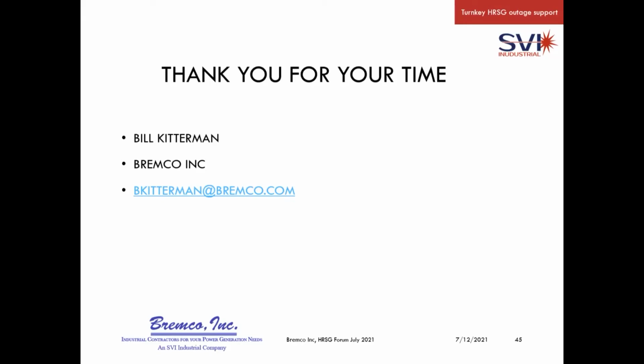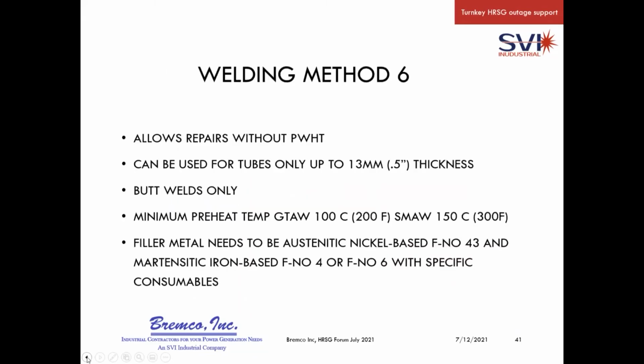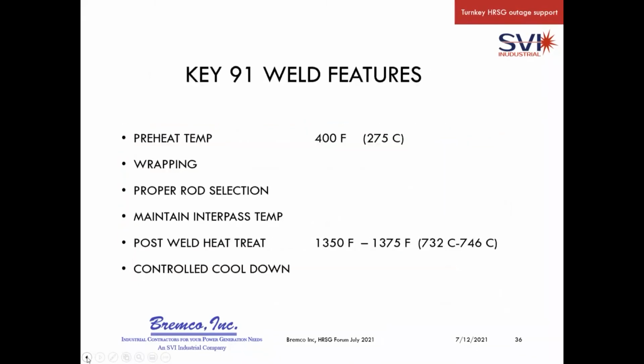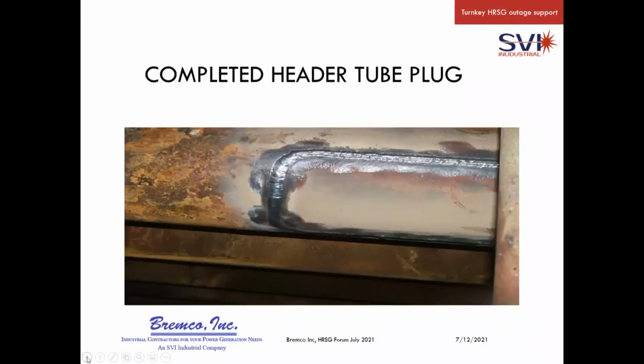On the other hand, if you cut a window in a P91 header, you inevitably end up with two long seam welds in that window running the length of the header for some distance. So even if you make round ends on that header plug, not the tube plug, but the window you cut in the header to get access, you've essentially got long seam welds in a P91 pipe, which has some significant weld strength penalties associated with it.